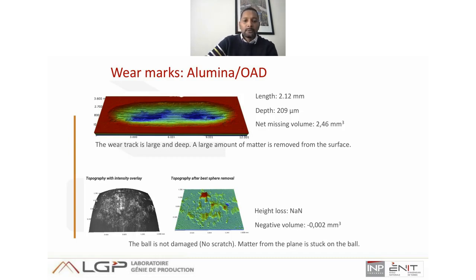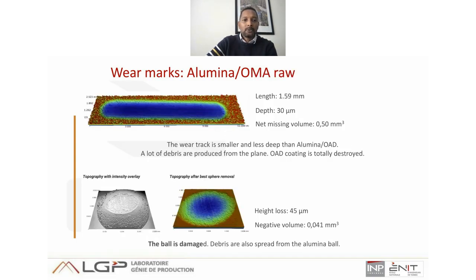On the surface of the ball, there is no loss of matter. On the contrary, there is no damage, no scratch on the surface, and some matter from the plate is stuck on the ball. This is why we have a negative volume during the measurement. When we compare this to the couple of alumina and raw OMA, we see that the length is decreasing. The depth is very low compared to OAD, 30 micrometers, and the net missing volume is 0.5.